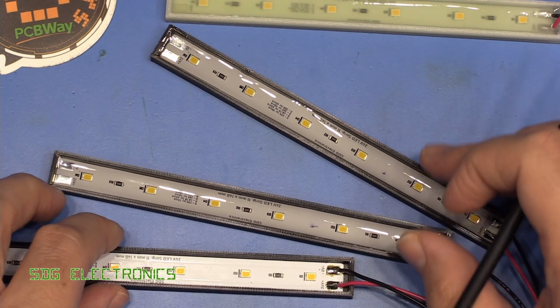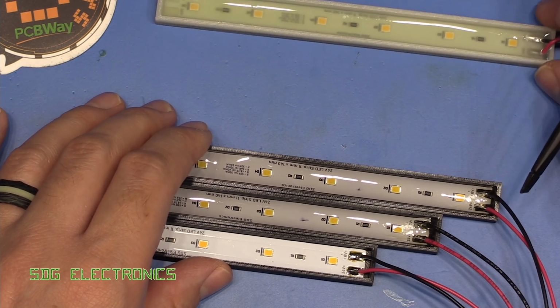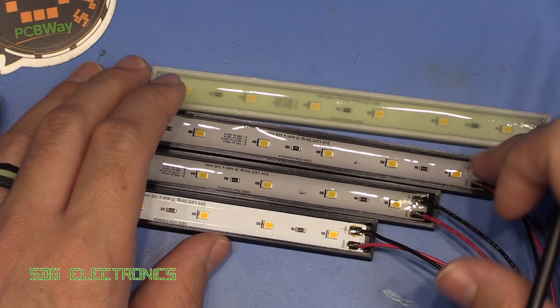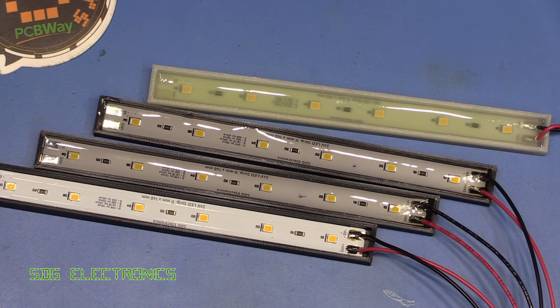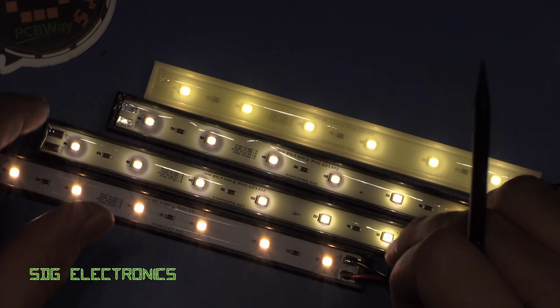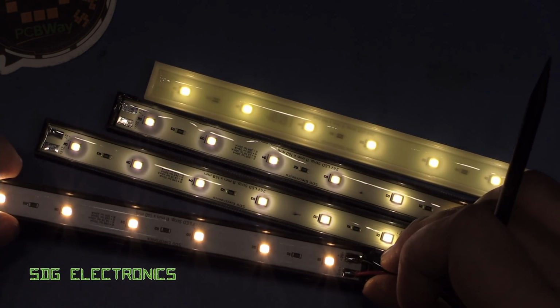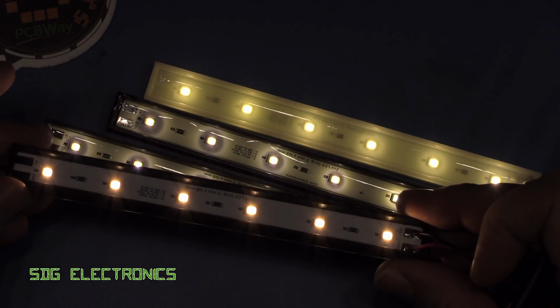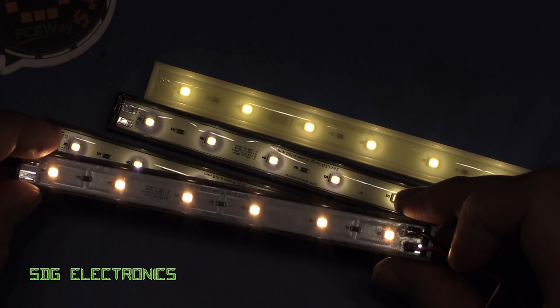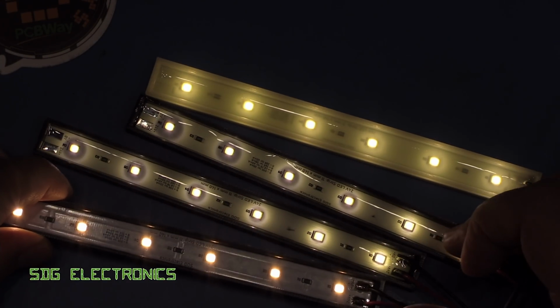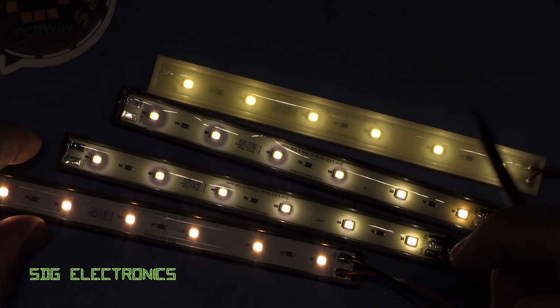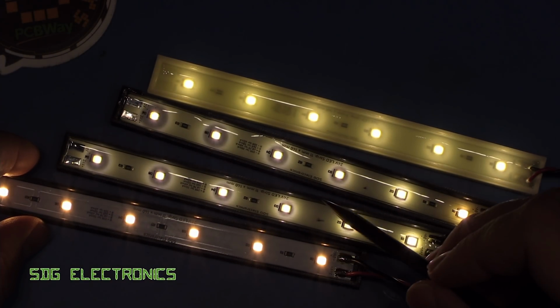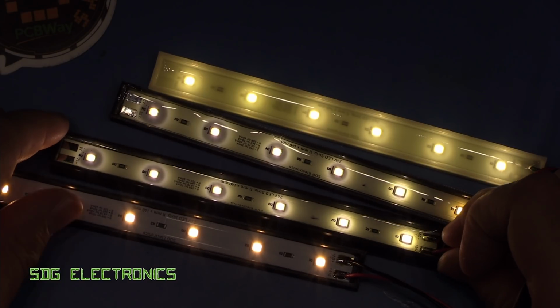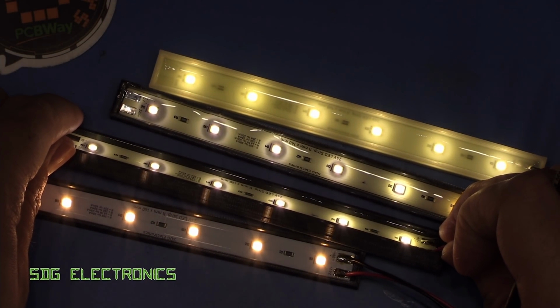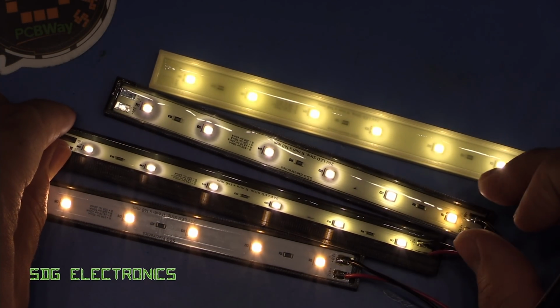So let's power them up and see if we can see any difference. We've also got the one with the glow-in-the-dark resin here as well. So let's power these up. These are now running at about 30 milliamps or so, so quite a low current. And first of all, the warm white is looking very nice and warm white, exactly as you'd expect. But there is quite a significant difference between these and the ones that are encased in resin. There's probably at least 1,000 Kelvin colour shift, quite a significant amount.